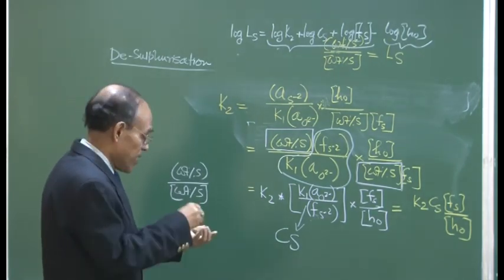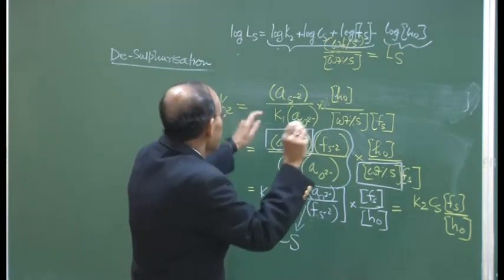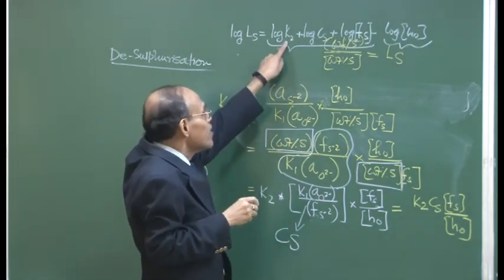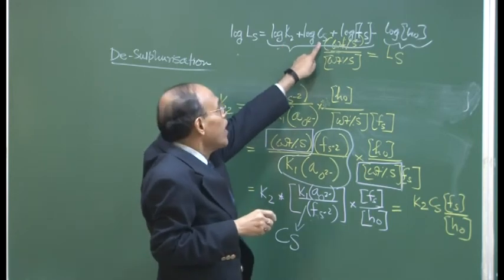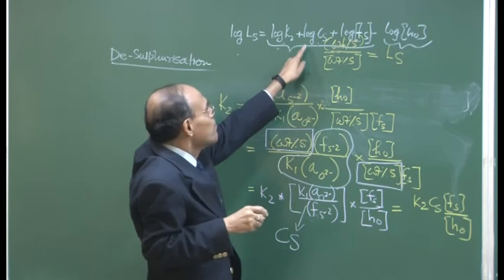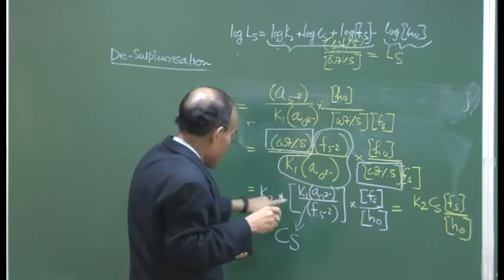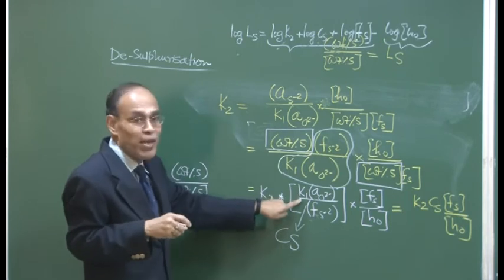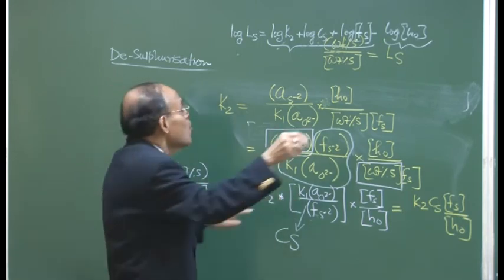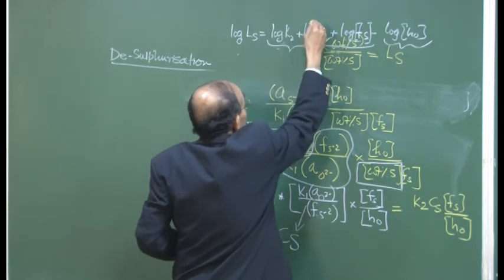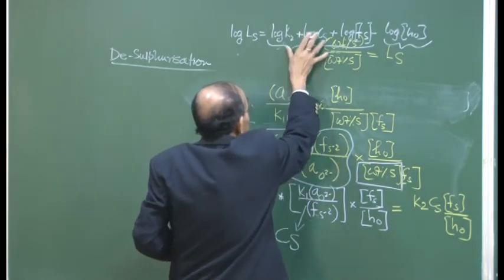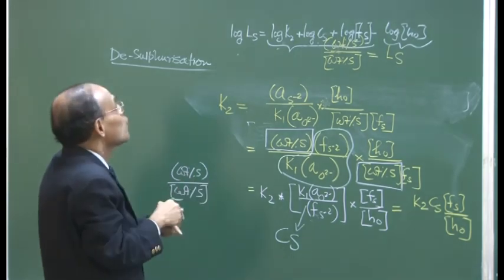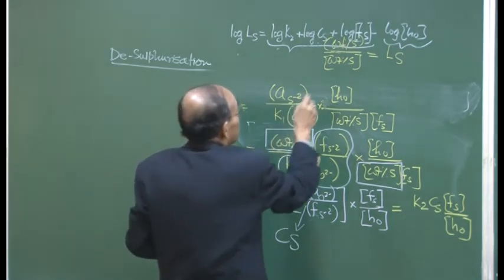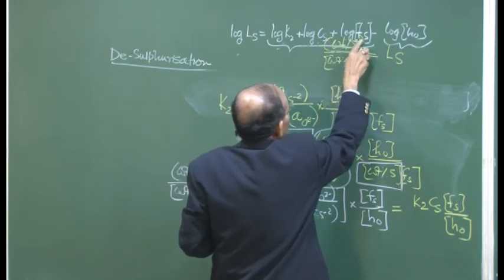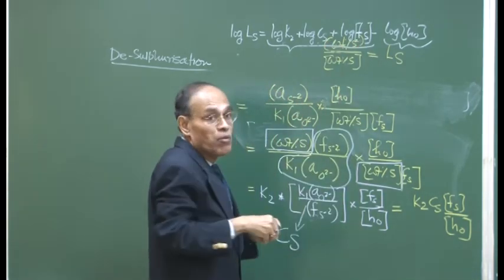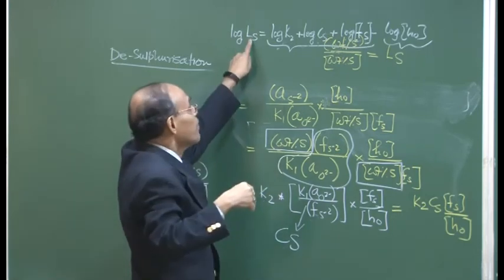And therefore, we can see that temperature will have an effect because the equilibrium constant is a function of temperature. From this particular relationship, the role of temperature is not quite obvious, because CS itself is a function of temperature, because CS contains an equilibrium constant which itself is a function of temperature. So this is also an implicit function of temperature. So temperature has a certain role, okay, may not be at that significant level. But it is understood from here clearly that the higher the activity coefficient of sulfur in the melt, the more will be the chances of getting a high value of LS.